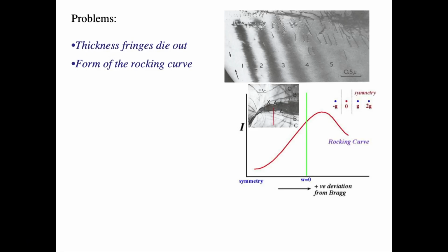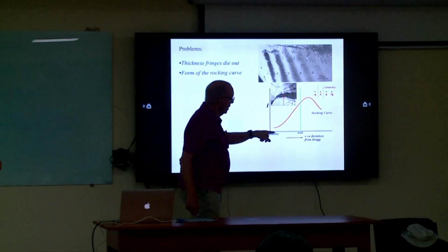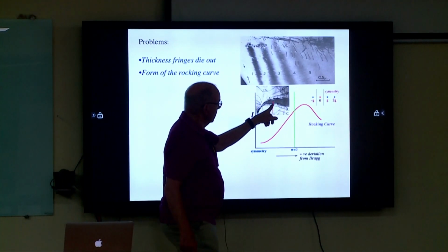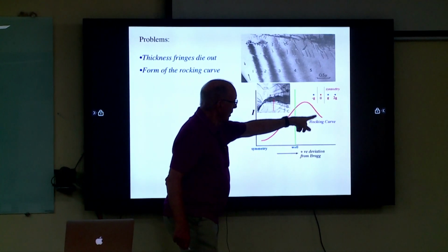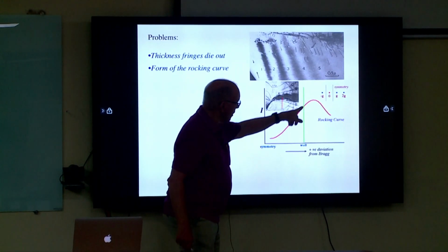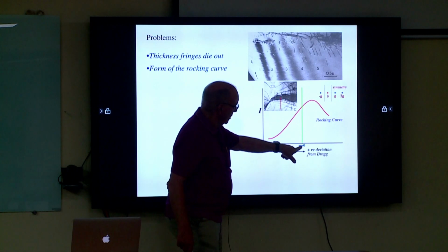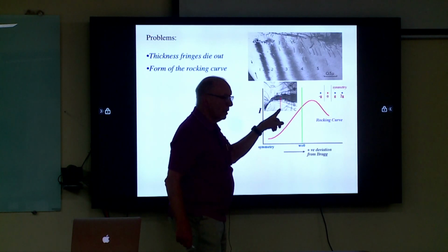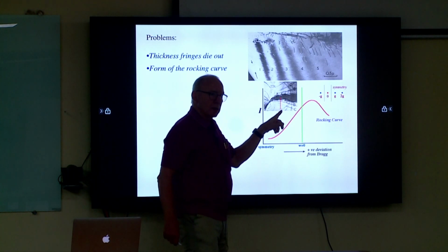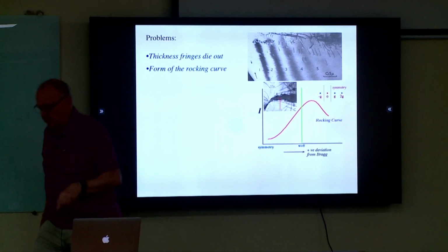And then here, if I were to take an intensity profile from the middle here, which will be the symmetry position going out, when I go through the first maximum here, which is the first dark thing, I have something like this. So my rocking curve would look asymmetric about the Bragg condition here. Why? That's not predicted by the geometrical theory either.